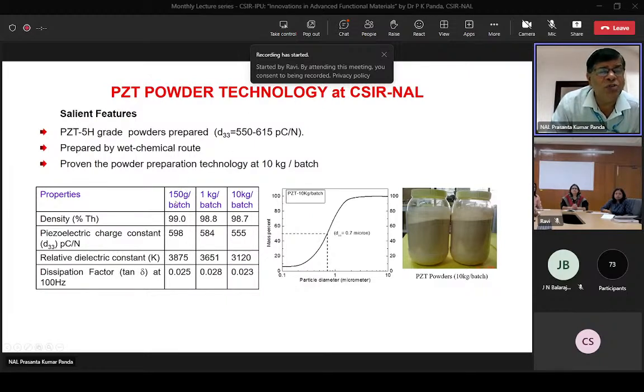So I will directly skip, finally. In the first project, we developed a large scale 150 gram batch piezoelectric material, which had nearly 600 picocoulomb per Newton, and then it was further upscaled up to a 1 kg batch in a CSIR 5-year plan project, and then further to 10 kg per batch. To upscale 550, which still has high D33 properties, and as you can see the particle size is less than 1 micron. That shows it is very fine powder, therefore the reactivity is very good when you make the bulk materials or for sintering.